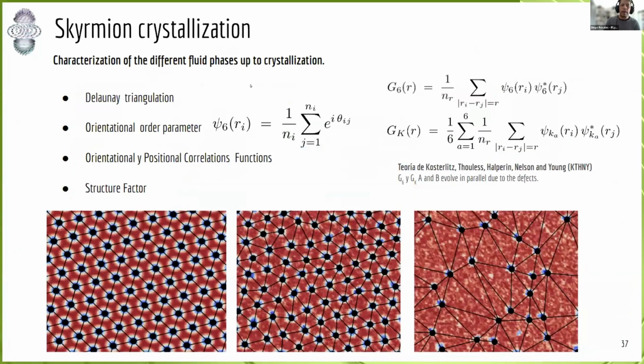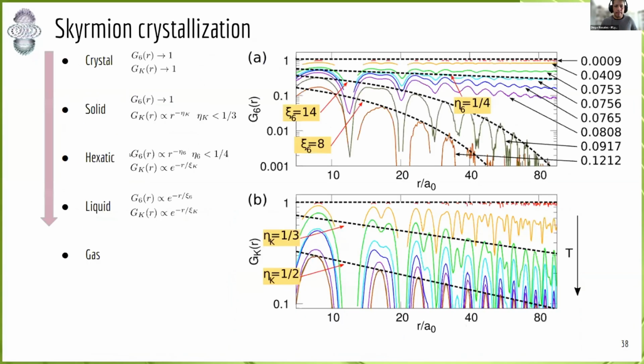We apply the Delaunay triangulation to identify the centers of the skyrmions, and we compute another specific order parameter to detect the topology of the phase, and compute two different correlation functions, positional and orientational, in order to detect different phases of these skyrmions. Maybe this is a little boring, but we compute the correlation function at different temperatures as a function of the distance, and we identify the different values of the exponent in the correlation functions. And we identify three or four different phases, actually.